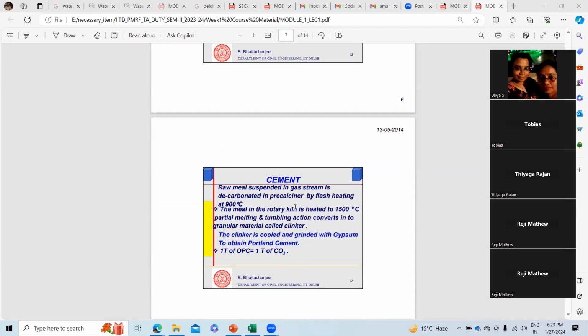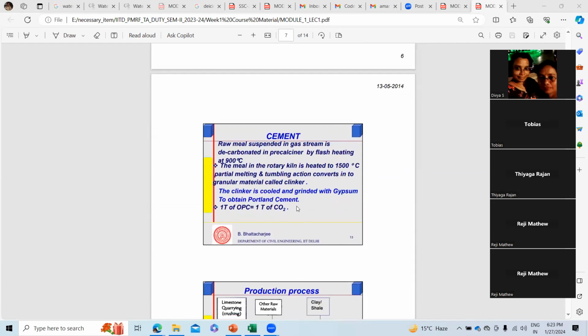Now the raw material suspension is also introduced here. The decarbonation process and the various stages of temperature that I have also explained, including 1500 degrees Celsius. During these temperatures, various cement compounds are formed. The cement compounds are C3A, C3S, C2S, C4AF. C3A means tricalcium aluminate, C2S is dicalcium silicate, and C4AF is tetracalcium aluminoferrite.